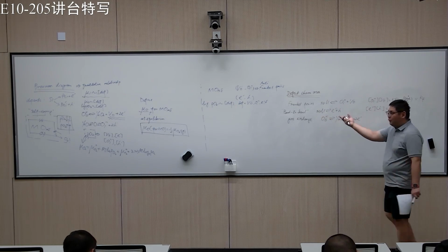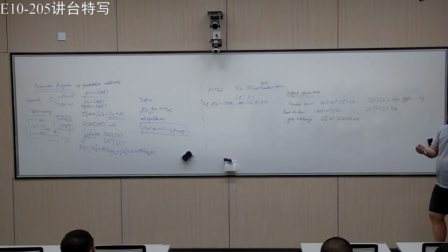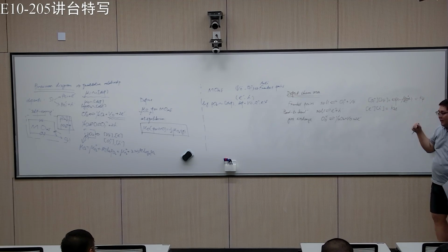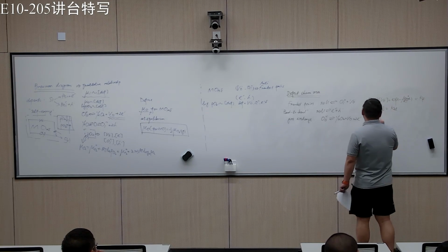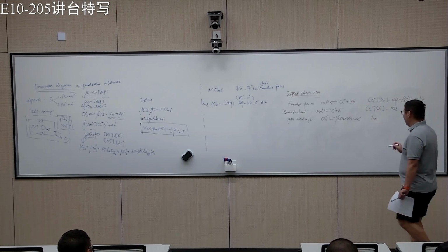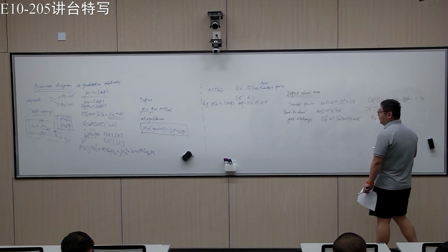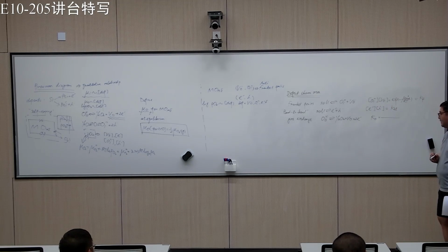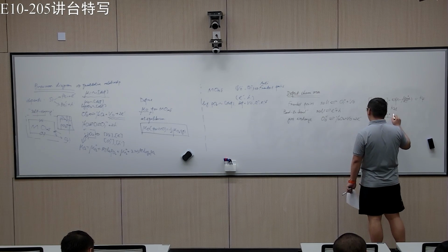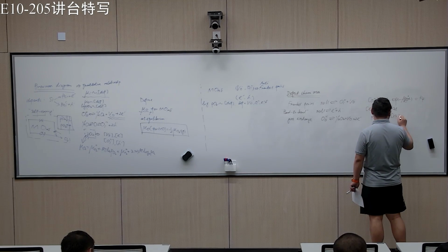Equivalently we can write it the other way depending on which way you are going, but they are actually the same because at the end of the day you have the Frenkel pair to connect these two. Let's say the equilibrium constant is KO. KO should be, if we follow the so-called mass action law, then PO2 to the 1/2 times OO.